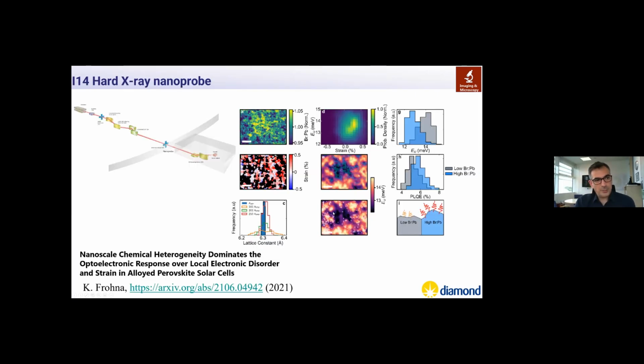The hard X-ray nanoprobe I-14 in this group is also a relatively new addition to the capability at Diamond. This is typically one of these very long beamlines that you find at a synchrotron, because you need to demagnify the beam. There are many beamlines like that in the world now. I-14 is one of the newest in the club, reaching typically around 50 nanometer resolution and pushing it down to 25 to 30 nanometers when they use ptychography.